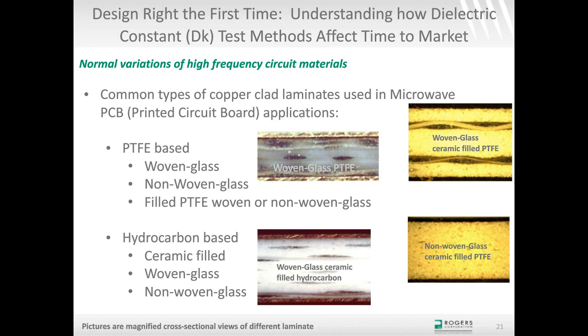The PTFE-based materials can be woven glass or non-woven glass, but typically are woven glass, and a lot of times it is ceramic filled with woven glass. The bottom right picture is actually a little unusual, and that is ceramic-filled PTFE with no woven glass. That's our RO3003, a laminate used in 77 gigahertz millimeter wave applications, and there are definitely some benefits to not having glass.